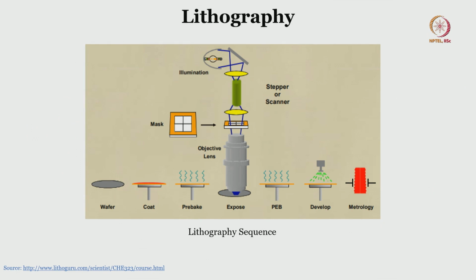So, the lithography sequence is that you start with a wafer, then you clean the wafer, pre-bake it to let the moisture get evaporated, then you spin coat the wafer. After spin coating, you can do soft bake. See, again the words are used in a slightly different format. Generally you will find pre bake, post bake as one term, or soft bake, hard bake as another term, both are the same. Okay.